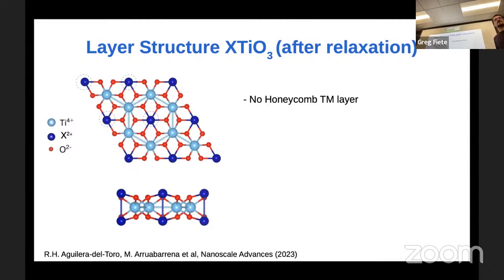So it's an interplay between the two. It will be interesting when you add more layers, if you put 2 or 3, when you will recover. Yes, that's interesting. In fact, we did already some preliminary tests about that. But the main problem is that it's strongly dependent on the compound, whether it's cobalt or iron. Then we have a mesh of tasks that we have to organize. So we already did some calculations for that. Maybe after you grow a few layers, you can see a situation where it's at a critical point where J1 is roughly equal to J2.